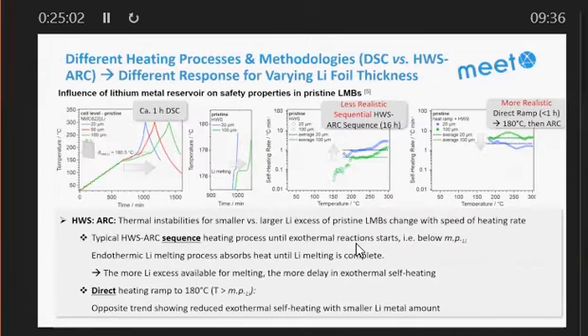Okay, if we look at what we do with the heating processes, as I said, we did very systematic studies. We found out that when we do 3 cells, everything is somehow different. Okay, and if we look, for example, at the DSC on the left, this is a 1-hour experiment. Then the DSC is done from room temperature until more than 300 degrees C. We see that when the lithium is thicker, the temperature moves to the right. So that means the temperature becomes more safe for the pristine LMB. So that's very interesting because a lot of people believe thin lithium is safer than thick lithium because we have less reactive components in the cell. But in this case, because the lithium melts and the lithium takes up heat during melting because it is an endothermal process, thick lithium is safer than thin lithium in the DSC measurement.